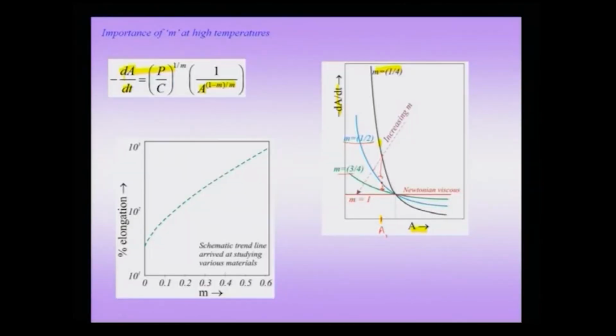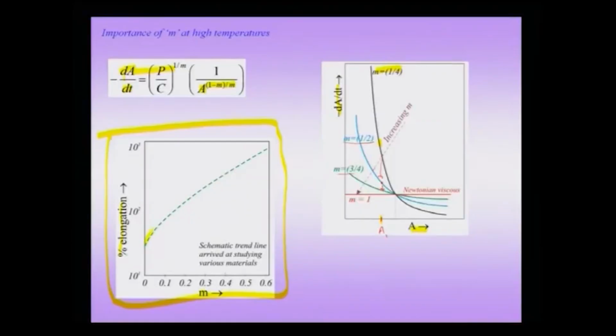Now, if you look at experimental results done on various specimens, you would notice in the curve on the left, which I have drawn in the box here, the percentage elongation versus m. Now this is comparing various materials under various conditions, and there you can arrive at a schematic trend line: if m is larger, then you get larger percentage elongation.